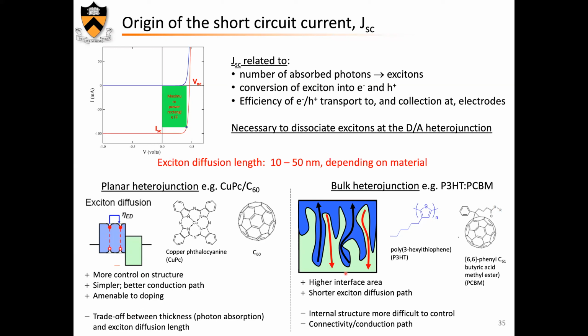People have tried to offset this balance by generating what are called bulk heterojunctions, where the two are mixed. Of course, that increases the interface area between the two materials, and it considerably shortens the exciton diffusion path. If an exciton is created right here, it only has to go a short distance to this interface. The difficulty is that it is much more difficult to control the internal structure of the two, the connectivity, the conduction path, and so on. So that leads to a lot of optimization, which from a scientific point of view may not be very interesting, but from a technological point of view is very, very important.